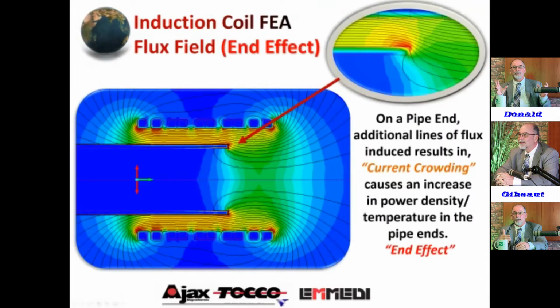There we go. Now here is another flux mapping. Here's the coil, copper coil winding going all the way around. This is a cross section. But you see the magnetic field and how it crowds together, and we get a depth of current penetration. But what we're trying to show here is a condition called current crowding. Remember in the video we showed of heating, that there was an overlap. That means the coil overlapped to the end of the part to compensate for the radiant losses coming out. And this is more of a swaging process here, or a heating up for an upset, but it shows this condition.